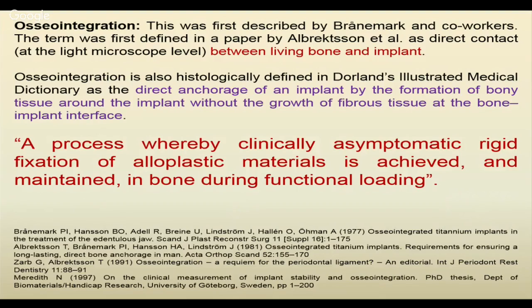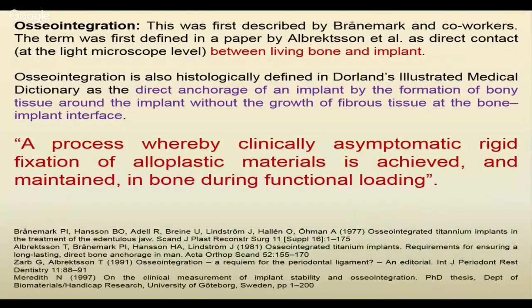So we need to have hierarchical porous topography, with also hierarchical roughness on the surface, along with interconnected porous structure, so that tissue can grow into it and cells can adhere on the surface of the material. That eventually causes tissue ongrowth and then tissue ingrowth, where you need the vasculature. A 100 micron pore size gives you vasculature, and then eventually it gives you biological fixation, or osseointegration, or osseoincorporation. The term osseoincorporation was introduced by Zimmer.